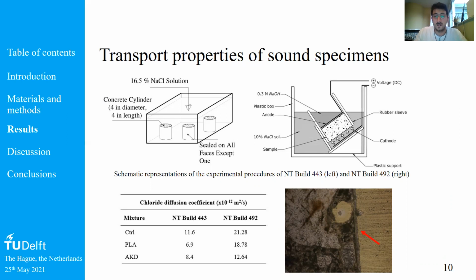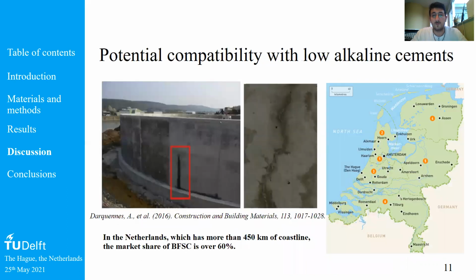So we basically evaluated quite a few qualities or characteristics of our material that could confirm the applicability of our healing agents with self-healing ordinary Portland mortar. What is also very important is that we know that, in general, for certain applications, especially for infrastructures that are exposed to pretty aggressive environments, such as with a high content of chlorides, it's common, especially here in the Netherlands, to use slag cements, especially with high content of slag, such as CEM III/B. And in a country like the Netherlands that has more than 450 kilometers of coastline, the market share of slag cement is over 60%.